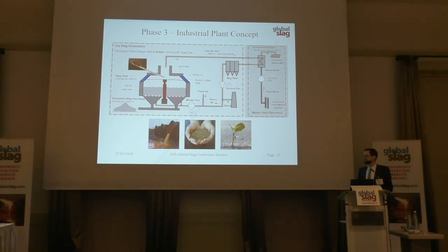Okay, so have you selected any kind of particular technology for waste heat recovery, organic Rankine cycle, anything like that? Normally in an integrated steel plant you have steam networks available, so let's say the cheapest solution would be having a boiler after the granulation process and feeding the steam network with our additionally produced steam. Okay, because 500 degrees is actually quite a high temperature. It's a quality source of waste heat. Yes, but the higher the temperature is, the higher is the efficiency of the steam boiler, for example. So if you have 300 degrees Celsius, you cannot extract that much energy from the air for steam production compared to an energy source of 500 degrees Celsius.